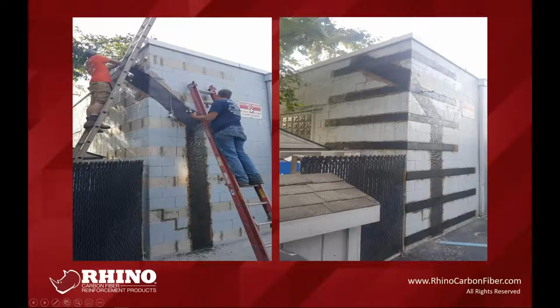So what we did was a multiple layered kind of thing. We did the crack repair here, goes up, goes around the corner. That's a standard crack repair after they composited it back in. And we use a thickened epoxy gel called anchoring epoxy to put in the mortar joints and mortise joints. Then we followed it up with a carbon fiber crack repair. That's a 12-inch wide bidirectional. And then we have a unidirectional that goes around for these corner straps.